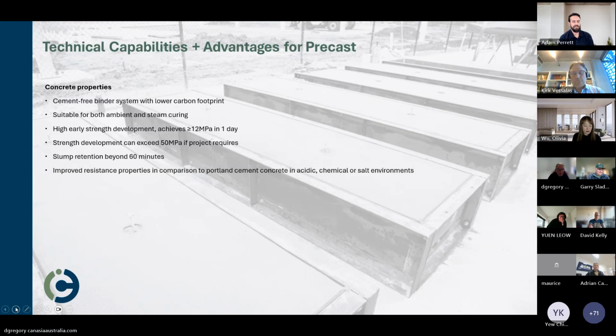Okay, what are the technical capabilities and advantages for the precast market, which we've particularly designed this presentation around today? As I've said several times already, this is a cement-free binder system, which gives a lower carbon footprint. And I'll give some figures later on in the presentation of the relative values. We do all our reactions at room temperature, and we've done pours anywhere from 15 degrees centigrade up to 40 degrees centigrade. You can use steam curing with this system, but it's not necessary.